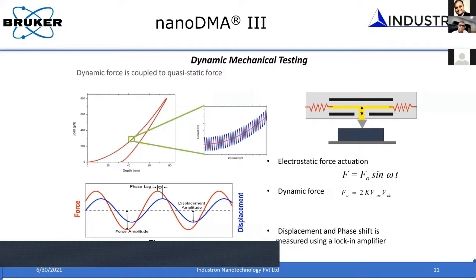So this is what I mentioned about the nanoDMA technique, where instead of just applying a quasi-static force and measuring the displacement, you can also apply a dynamic force and then measure the response. For example, if you apply an oscillatory force and measure the oscillatory displacement response, if the material is elastic, you will not see a phase shift between the force and the displacement, and the force that you are applying will be in phase with the displacement that you measure. But if you do it on a viscoelastic material, there will be a delay between the force that you apply and the displacement that you measure. That will induce a shift in phase.